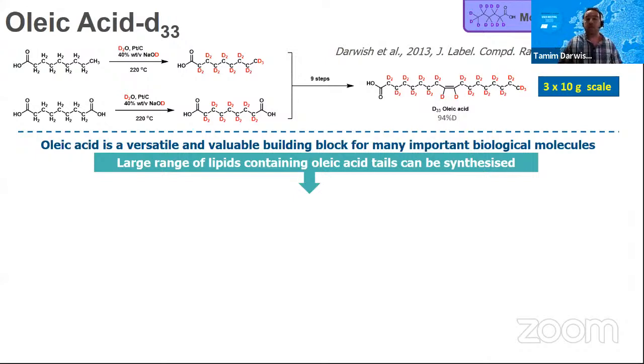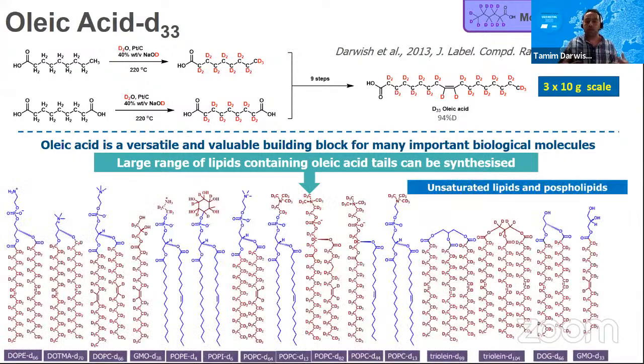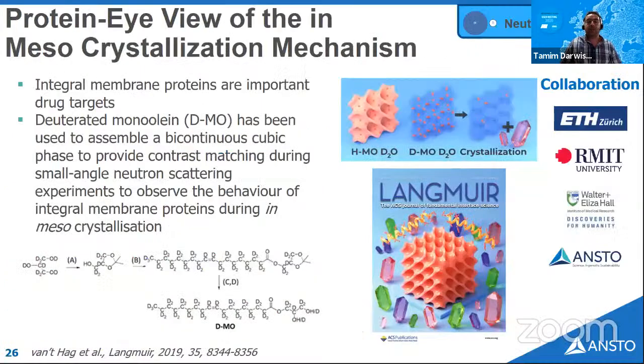So oleic acid, we've been deuterating this and producing it for our users on really large scale, about 10 gram scale. We can do it three times in a very short period of time because we have scaled up and optimized the reactions. It's about 9 steps to make. And because of this, we can produce a variety of different labeled molecules and lipids. DOPE to POPC, trioleins, GMOs. And because of this diversity of deuterated molecules and the scale that we can produce, we are able to produce really high impact science with our users.